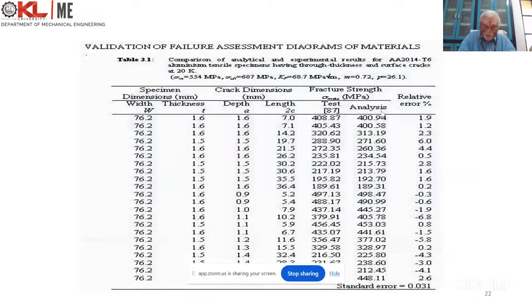If you look into it, a lot of different diameters, widths, plate thicknesses and crack dimensions were given, fracture strength was measured, and through analysis also. What we see is that we are able to predict below 5% error. That 5% you have to accommodate while fixing the factor of safety for the component.